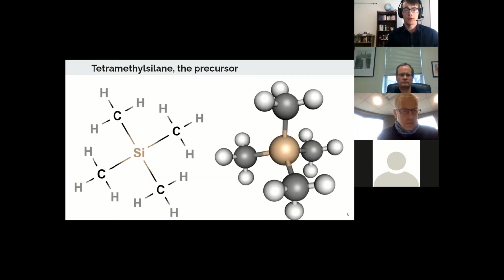Interestingly, this process transforms an organic precursor, the TMS, into an inorganic material, silicon carbide. Tetramethylsilane is nonpolar and has a high vapor pressure. It has a boiling point of only 26 degrees Celsius. So if you get just above room temperature, it starts to boil. This slide details the structure of TMS, which is tetrahedral at both carbon and silicon. The left-hand image is a structural formula, and the right-hand image is a 3D ball and stick model of TMS.